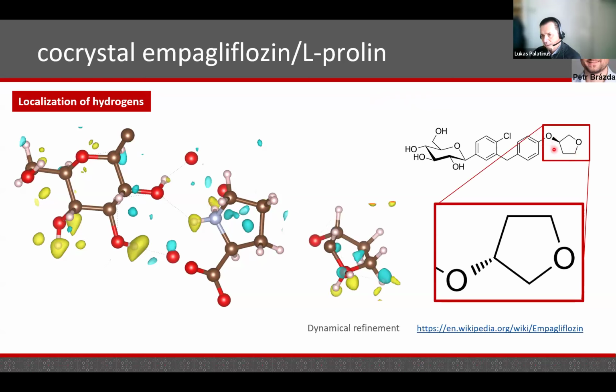So this was the expected structural formula. This is the same, just rotated to match it with the experimental data. And here you see there are two very clear maxima around an oxygen atom, which would make this oxygen 4-bonded, which is an obvious nonsense.